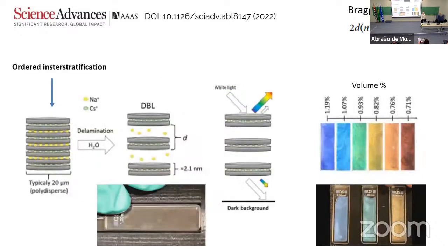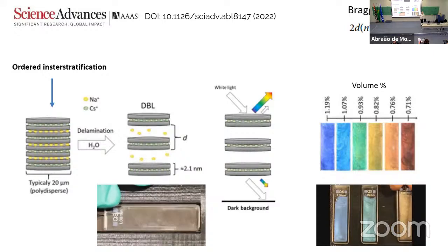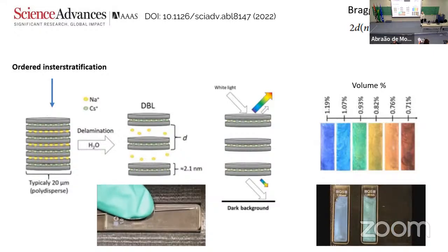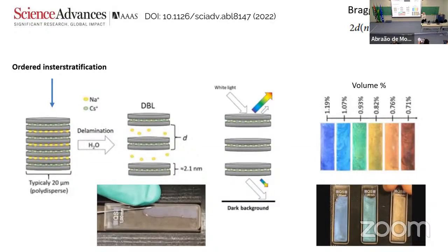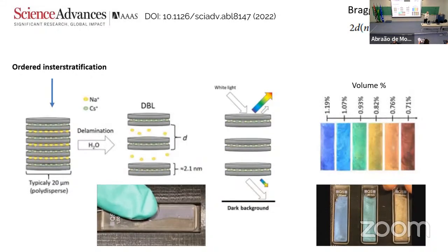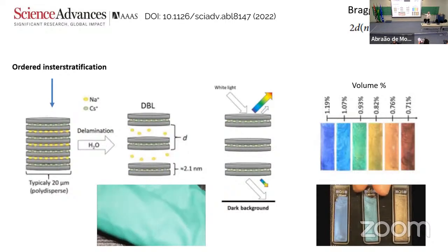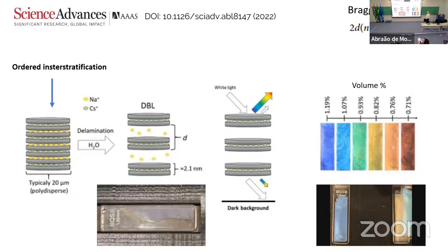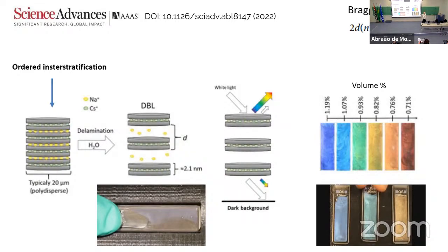We did the ordered interstratification in the clay. So we put cesium ions in every second interlayer. Then we did the delamination. So now we have the suspension of platelets that are not single clay platelets, but double clay platelets with cesium in between them. From that suspension, we got very bright colors. The reason for this is that these double layers are less transparent than the single layers. The single layers are almost fully transparent.